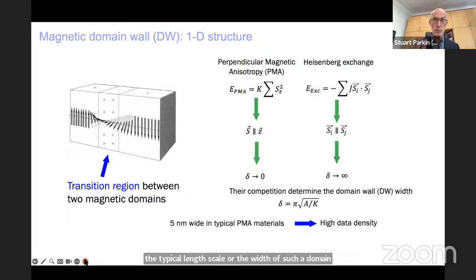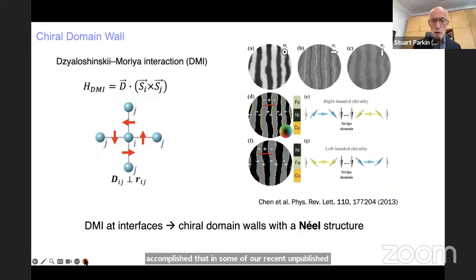And this means, in particular for Racetrack, we can imagine building structures with 5 nanometer wide domain walls spaced a few nanometers apart. And I want to show you that essentially we've accomplished that in some of our recent unpublished work. However, if we move from a one-dimensional system or one-dimensional domain wall, then in a two-dimensional system, there can be, in addition, more interesting interactions.